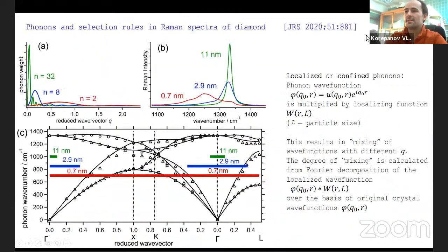And coming to the way we describe the phonons in nanoscale materials, in these 3 figures we have the same phenomenon displayed from 3 different points of view. We have phonon dispersion in the bottom, calculated and experimental. Phonon dispersion is the dependence of the phonon energy on the wave vector. It is 3-dimensional, and the way physicists usually plot it is as a cross-section along high symmetry directions.